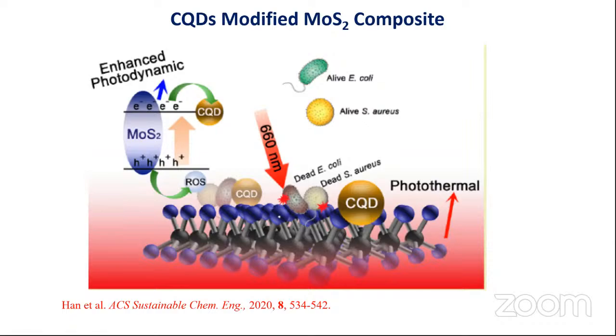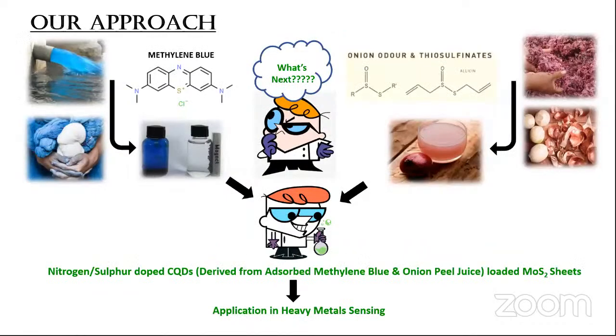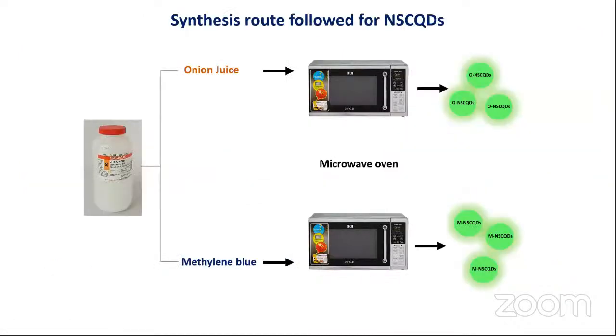Our approach is that we are using waste material. One is dye, and the second is onion peel extract, which comes out of daily waste. We take those waste materials and do the carbonization. In both cases nitrogen and sulfur are present, so we are getting nitrogen-sulfur doped carbon quantum dots. After synthesizing, we are going to use them for heavy metal ion sensing. This is the synthesis route we are following.